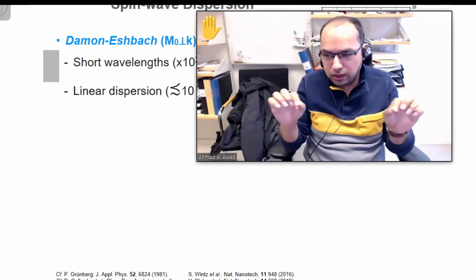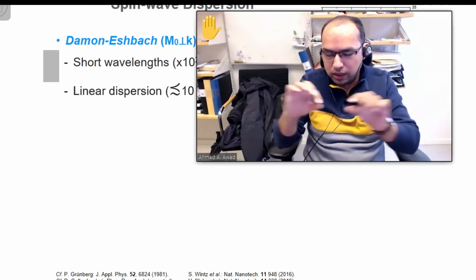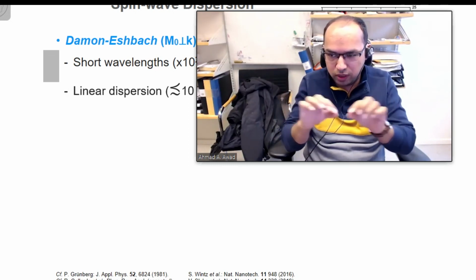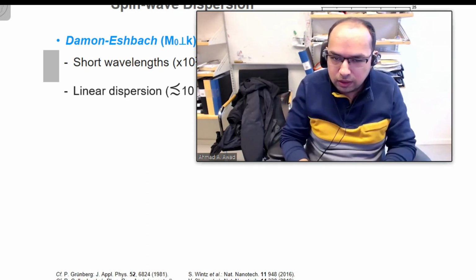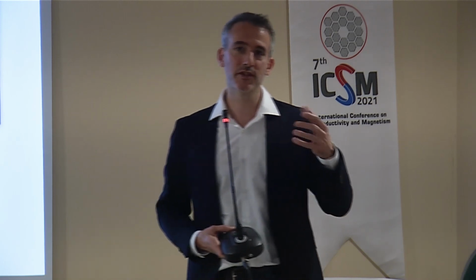And the second question regarding the shape. You see that the pattern is basically on one side of this narrow region of the metal. Is this due to variation of the metallic... I'm not sure. It could be a variation of the electrode, it could be a variation of the film, it could be a variation of the thickness of the GGG. There we actually have some 100 nanometer variation of the thickness of the GGG behind it, and that could lead to a different temperature locally.